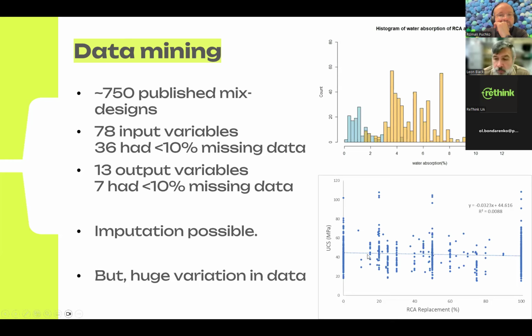When we plotted for the 750 mix designs, we plotted the percentage of recycled aggregates in the mix versus the unconfined compressive strength at 28 days. And we can see that because of the interfacial transition zone, there is a general drop in strength, ever so slight, but there is a huge scatter in this data. Okay, it becomes very difficult to say with confidence that this is our trend line when there is such significant scatter in the data. So we had to think, what else could we do?